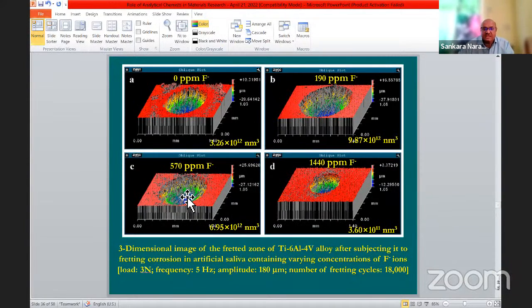Okay, this is the damaged area, and we can calculate the wear volume by using the x, y, and z-axis values. When we calculated the wear volume, in the absence of fluoride, the wear volume is about 3.26 × 10^12 nm³. When we added fluoride ions, about 200 ppm, it increased from 3.26 to 9.87. So the wear volume increased.